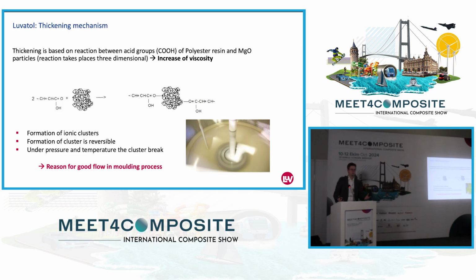If you don't have it, you can put as much MgO in there as you want. You get, of course, a higher viscosity because you insert a lot of powder, but you will not have the thickening effect, which helps you to have a better molding process and have a longer-lasting SMC at the end, which you can store.